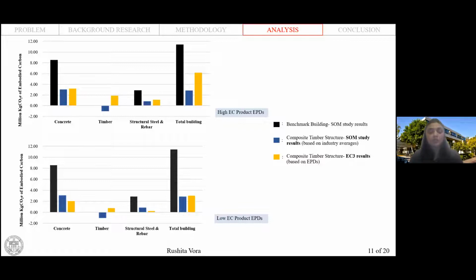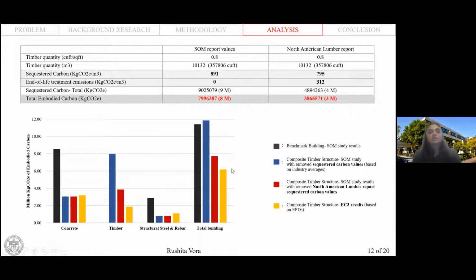Secondly, and more importantly, the main difference in these two methods is how they report the embodied carbon for timber. The published embodied carbon results for timber have a net negative value, whereas the EC3 tool gives a positive value. This is because the published results accounted for the carbon that is sequestered by wood, whereas the EC3 tool, due to its system boundaries, does not account for carbon sequestration. So the next step was to see how the timber would perform had the carbon sequestered not been accounted for.